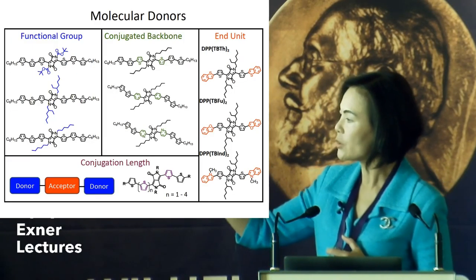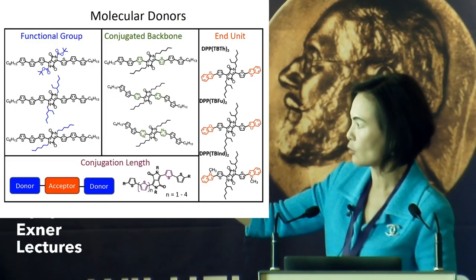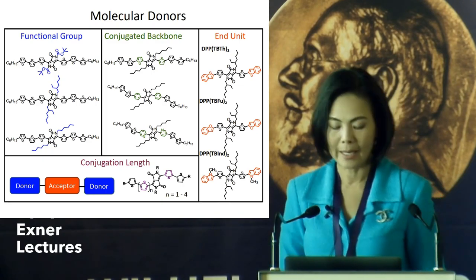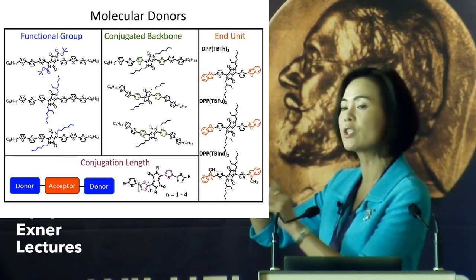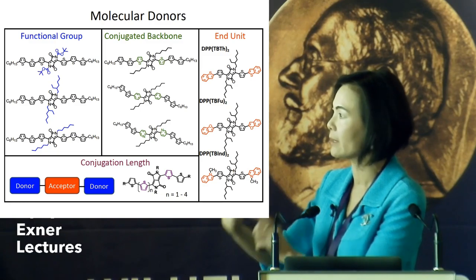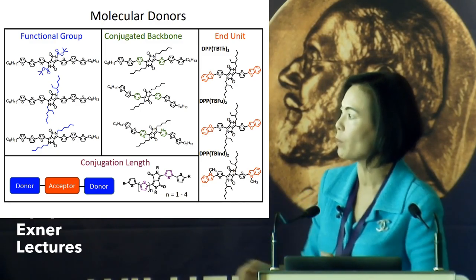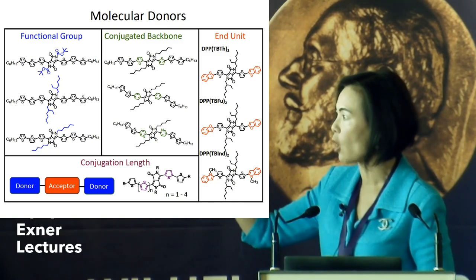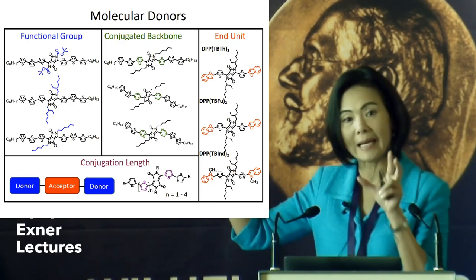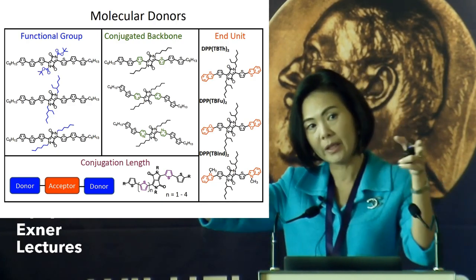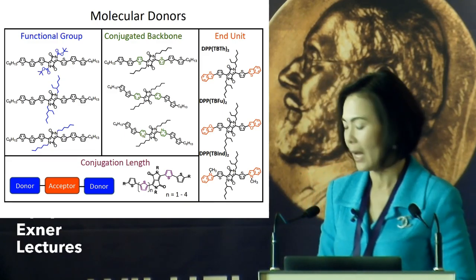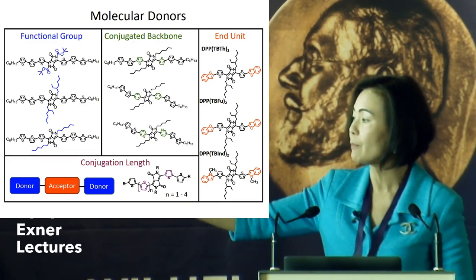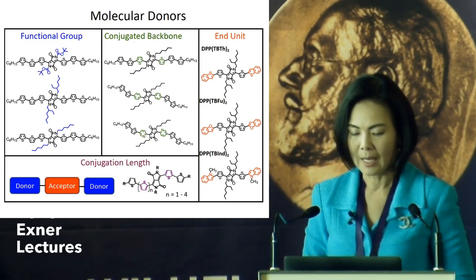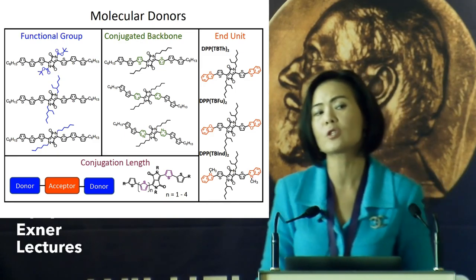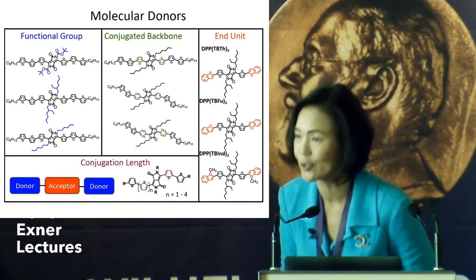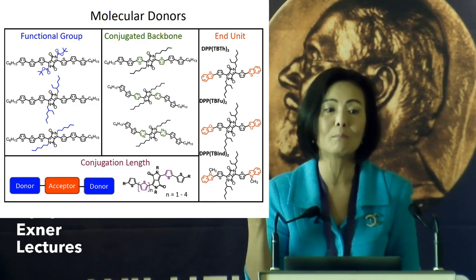And so we're using a conjugated molecule. And in this case, we systematically change the functional groups, like for example, the side chain, the conjugated backbone, and also the end unit. And we can vary the length of the molecule. And we're using the donor-acceptor-donor type of framework. And so when we first tried to submit the paper, it took 2 years. We got rejected by 5 journals.